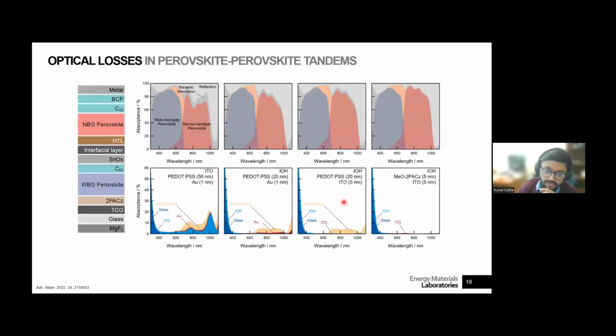And then we try to optimize the stack by basically changing first of all this ITO layer and replacing it with IOH, and that's to reduce the free carrier absorption in the near infrared. And at the same time, we reduce the thickness of this PEDOT:PSS layer from 50 to 20 nanometers, and you can clearly see that this parasitic absorption contribution goes down significantly. The next step to do would be to replace this gold layer with ITO. So this red part also goes down.